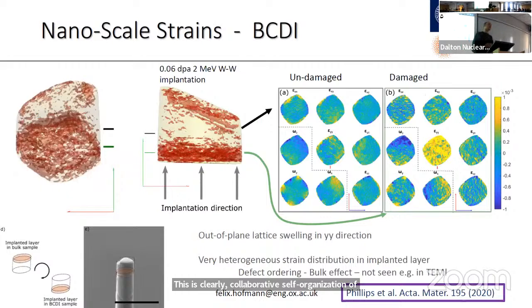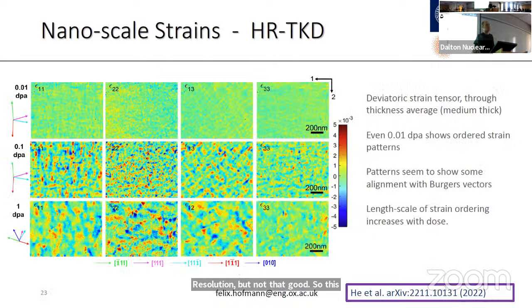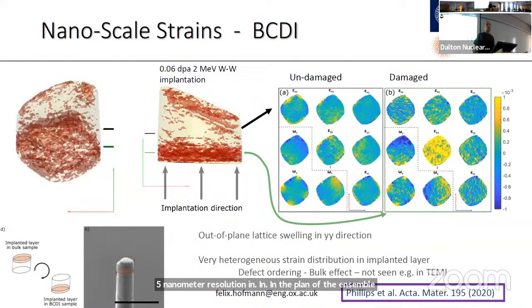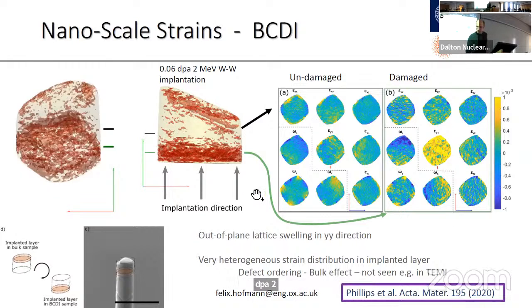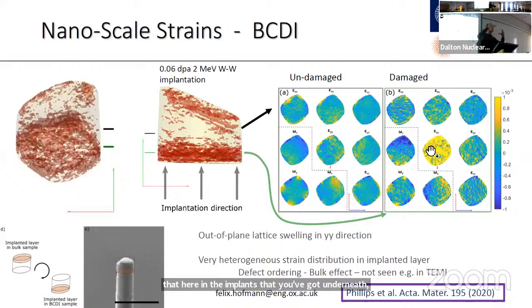And we also have a way of measuring this with 3D resolution, but not as good. So this was about 5 nanometer resolution in the plane of the sample, 5 to 10. These are X-ray measurements where we can resolve the full strain tensor in the sample with about 25 nanometer resolution in all 3 directions, and we get all 6 components of the strain tensor. So this is 0.06 dpa, 2 MeV tungsten, and all that I wanted to show is that here, the implantation was from underneath, and in this implanted layer you can clearly see strong heterogeneity of the strain field, compared to the much more uniform strain field in the undamaged region.